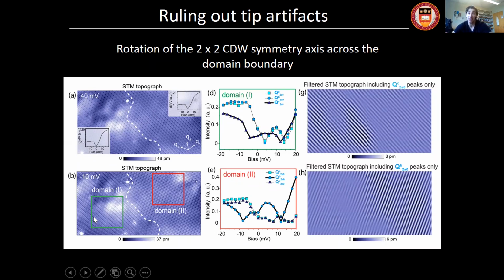And then if you do the same analysis as before, you take a DOS map here, you take a DOS map there, you can plot the intensity profile for these two regions. You're always going to see one direction that's different, but that direction is going to be distinct between the two. In domain 1, the green region, QC, the C direction, is the one that's distinct, while the other two are nearly the same. And in domain 2, you will have QB that's different, and QA and QC are nearly the same. So again, the reflection symmetry, or the C2 symmetry of this state, rotates across the domain boundary.